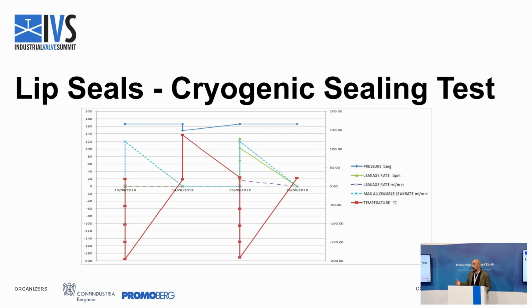We pressurize the device, then we go down to minus 196. We go up to ambient temperature. Sorry, we go up to 140 degrees in this case, but we can also choose different temperature, of course. Then we go down again to ambient temperature, and then we go down again to cryogenic conditions. And during all this pattern, we can control that the leakage that we detect is hopefully zero, or at least much below the general maximum allowable leakage given from the various certifications or the various qualification processes.